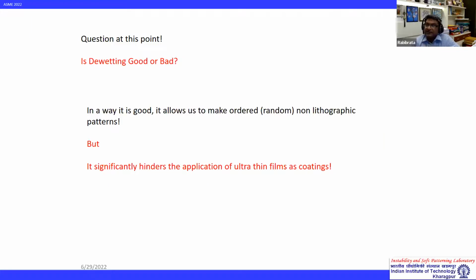Well, our forefathers actually did not know this much physics, but they realized that if you have a single layer coating, the thickness of the layer might be too low, and eventually this layer might disintegrate following exactly the same physics, right? So this is why you need to go for a slightly thicker layer. Of course, there are application areas where you'd like to have a thinner coating. One example is spectacles, most of which now contain some sort of coating, anti-reflection, anti-smear, this, that.